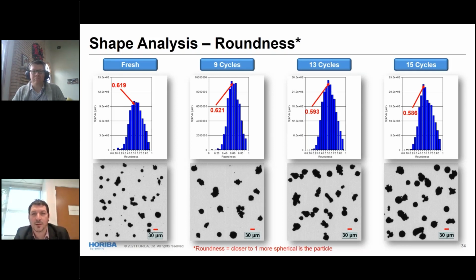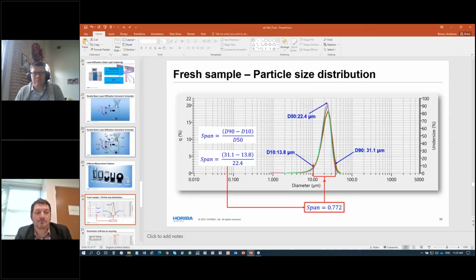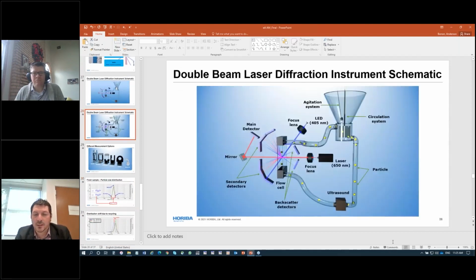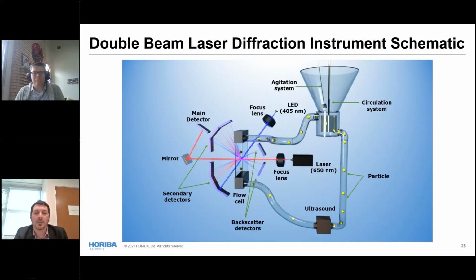So the other question was about the wavelength of the laser, the color of the laser. Does it make a difference to the data? It does. The reason why we have 2 different light sources is that there's an optimal intensity of scattering that depends on the wavelength of the light and the diameter of the particle. When you have larger particles, 1 micron or more, you're going to scatter mainly the red laser, so the data you have for those particles mainly comes from laser diffraction with the red laser. And as your particles get smaller, they start to scatter more of the blue light.